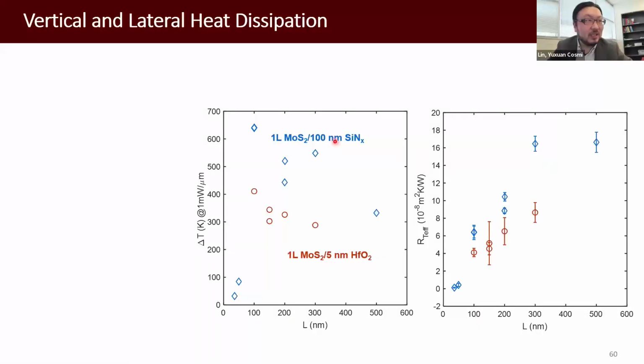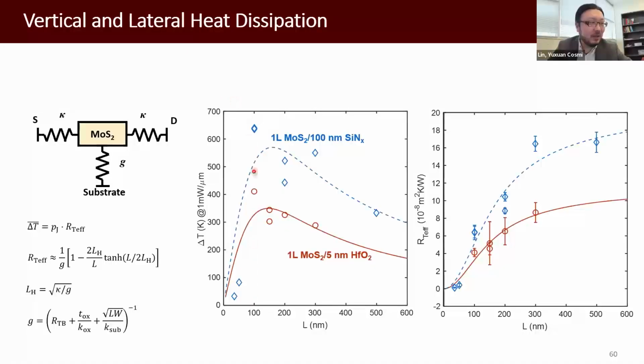These are two different back-gate dielectrics for monolayer MoS2 with different channel lengths. We plot the temperature rise and the effective thermal resistivity for these two data sets. And we can see a boundary around 100 nanometers. They have opposite trends for the temperature rise. Basically, for longer channel length, the heat dissipation is dominated by the out-of-plane dissipation. But when the channel length is smaller, the lateral dissipation through the MoS2 into the contact becomes helpful. So that can actually make the temperature increase smaller. That's why we see this non-monotonic trend.